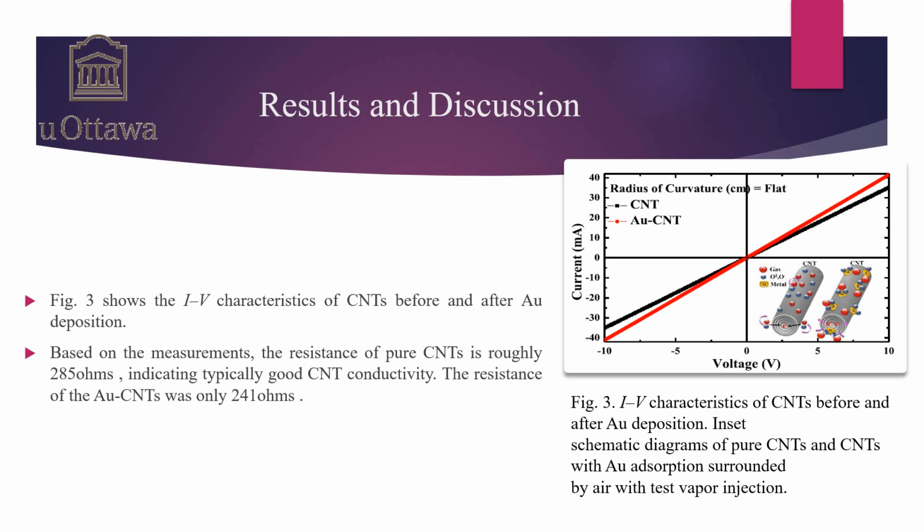The microscopic image shows that Au nanoclusters did not form interconnecting conducting pathways between Au CNTs, so the decrease in resistance must have resulted from net charge transfer between the Au nanoclusters and the Au CNTs. It is well known that addition of small amounts of noble metals such as Au to the elements can promote not only gas sensitivity but also the rate of response. Larger sensitivities observed for multi-walled carbon nanotubes with Au should be attributed to the enhanced interaction of multi-walled surfaces.